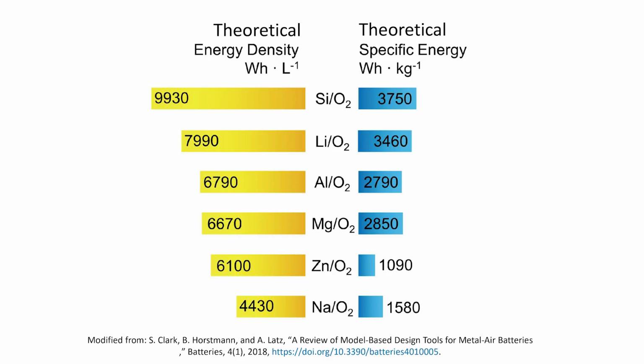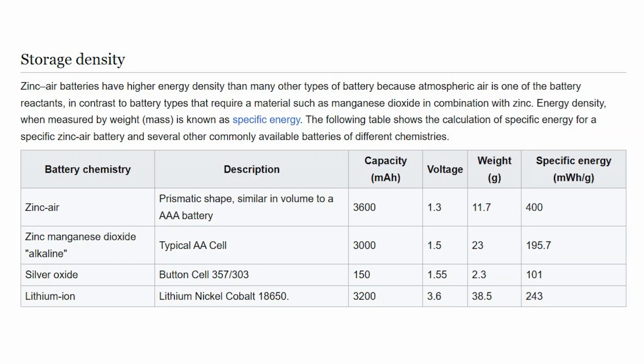Theoretically, it's like 6,000 watt hours per liter. In practice, you can get, I think, 1,400, like these little button cells. Not a very high voltage, though. Lithium-ion batteries will operate at 4 volts, 3 volts, somewhere in that range. But because zinc-air batteries use a water-based electrolyte, which on the one hand is a big advantage for sustainability and safety, they're limited to the electrochemical stability window of water, which is typically about 1.2 volts theoretically.